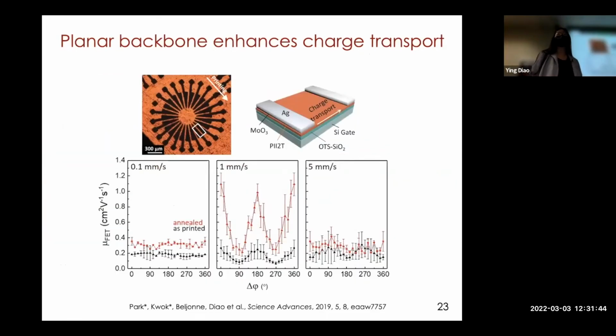So, how does that matter? Even small changes in polymer conformation can radically change optoelectronic properties. To assess how charge transport, the speed of a charge carrier, differs in these different polymer structures, we made transistor devices. What you're looking at is an orange film, the conjugated polymer thin film that's being printed, and the black regions are electrodes. We measure the charge transport between the two electrodes over 360 degrees. We found that for the chiral crystal mediated assembly pathway, there is no modulation of the speed of the charge carrier when we do this over 360 degrees.